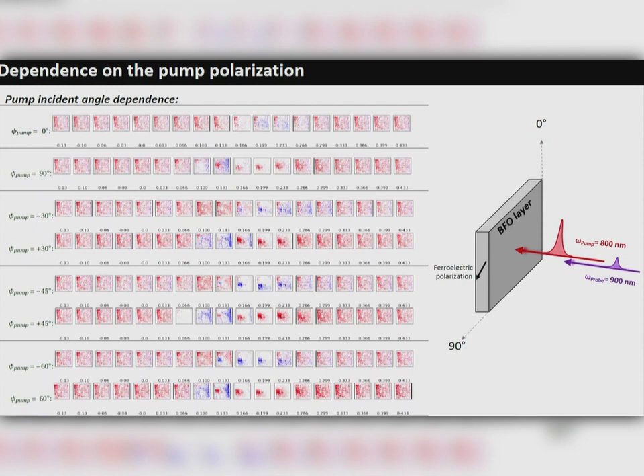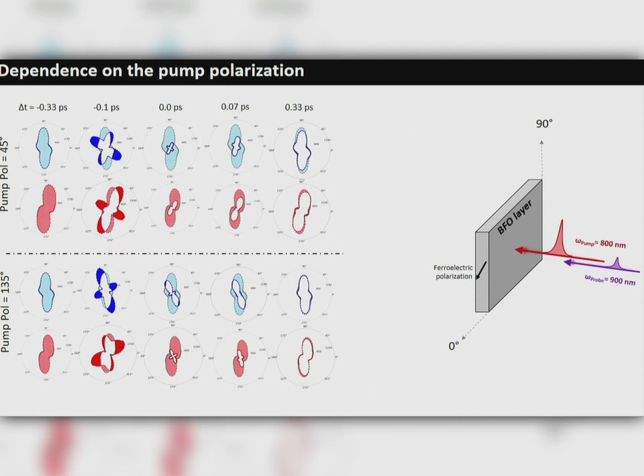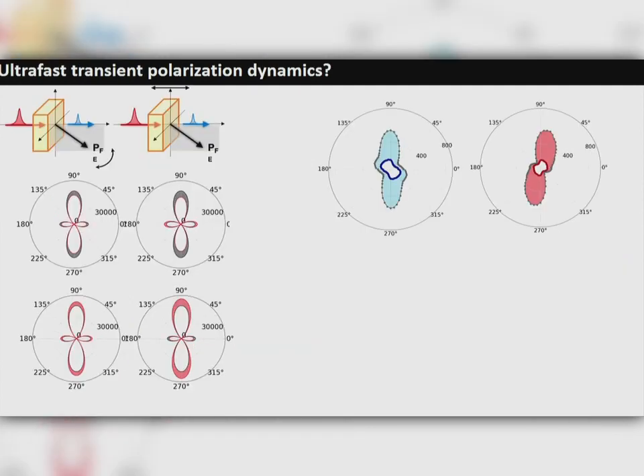So that put the finger on the fact that it's maybe the polarization which is induced by optical rectification. And actually, you can also follow how the angular dependence evolves with time, and you can see a clear change if you, for example, look at the pump polarization at 45 degrees and the one at 135 degrees. So basically, this is where we are now, and this is what we're trying to understand.